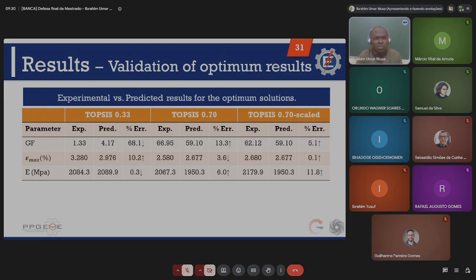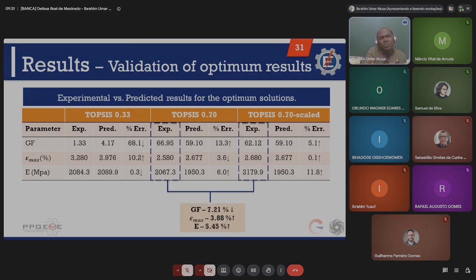For the first, TOPSIS 33, we can see that the maximum working strain and the modulus of elasticity were successfully validated with minimal error, while in the case of the gauge factor, there is a very big error margin, which suggests that the model must have overestimated the results. For the TOPSIS 70, all the responses were successfully experimentally validated with minimal error, and with this scaling, we were able to see that it successfully mitigated the stiffness effect imposed by the embedding.